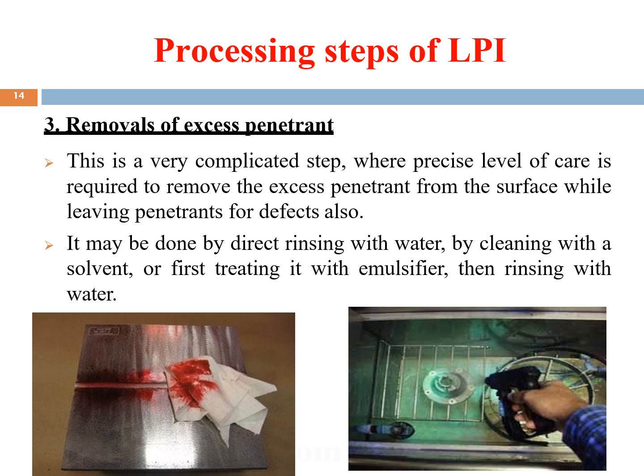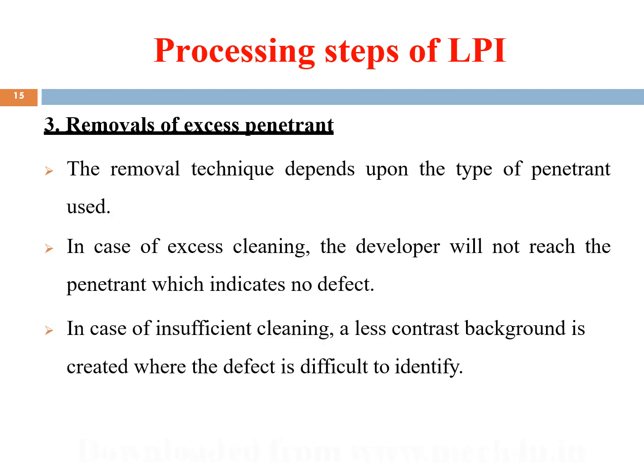But the removal of the excess penetrant is a very important and complicated step, right? If excessive cleaning takes place, the penetrant will be removed completely and the developer will not reach the penetrant. The developer has to reach the penetrant and draw it outside. So if there is excessive cleaning, the developer will not be able to reach the penetrant, which indicates that there won't be any defect. That is an error that can occur.